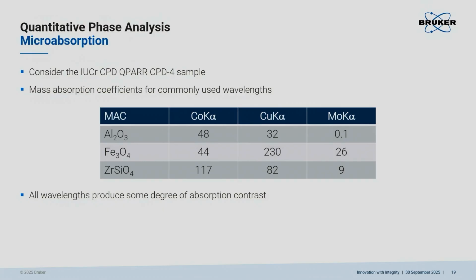So in this particular case, you see here values like 48, 44, same order of magnitude, 117. This is more than a factor of 2. You will already see microabsorption effects. For copper, it is pretty dominant, pretty clear between corundum and iron oxide. And moly here, 0.1 versus 26. This is already a lot. More than 2 orders of magnitude. So changing the wavelength may sometimes help. The take-home message is, if you want to do quant, calculate the mass absorption coefficients and check if there are significant differences. If there are, then you have to be prepared, at least in mind, that you will have significant